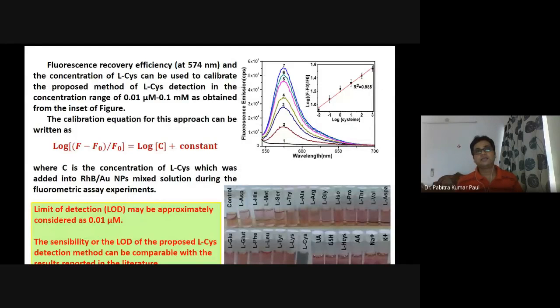And we plotted here the fluorescence recovery efficiency at 574 nanometer. This is the emission of the rhodamine B, and we have designed a calibration curve this way. And this is the steady state. From the steady state measurement, you can easily calibrate the sensor in this way by this equation. From this equation, you see here it is very much linear, and in our observations, we found that the limit of detection of this sample is about 0.01 micromolar.